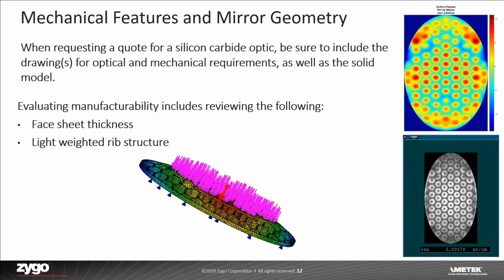As it relates to the lightweighting rib structure, the wall thickness of the ribs is limited by certain substrate manufacturers. So if there's a tolerance that is a must-have, that might steer us towards one manufacturer over another. Different suppliers have different parameters for the cross-section thickness, volume, and pocket patterns.